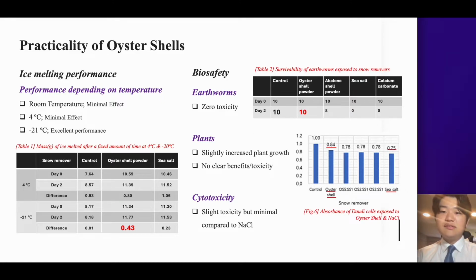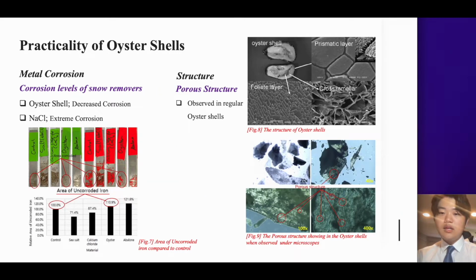As for cells, as seen in Figure 6, oyster shells showed slightly higher toxicity compared to the control, but when compared to salt, oyster shells showed a significantly lower level of toxicity. In addition, in terms of metal corrosion characteristics, oyster shells showed a surprising result of reduced metal corrosion. As you can see from Figure 7, with the level of metal corrosion of the control as a reference value at 100%, the level of area for no metal corrosion for oyster shells was 110.9%, confirming a decrease in metal corrosion.